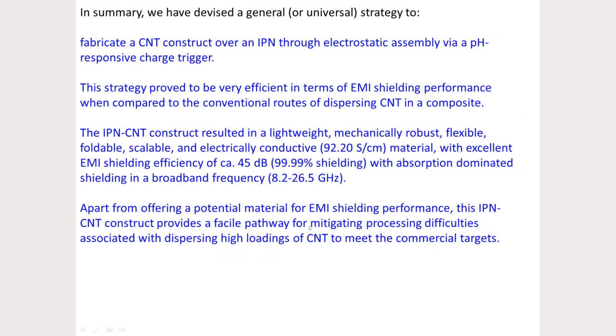So in summary, we have designed a general, universal strategy to fabricate a CNT construct over an IPN through electrostatic assembly. This strategy proved to be very efficient in terms of shielding performance. The construct is quite lightweight, as I showed you, and mechanically robust, because we have subjected these membranes to different bending cycles, and it could withstand 10,000 bending cycles. It shows a very high conductivity and a very high shielding effectiveness of about 45 dB in a wide frequency range. Apart from this, it offers a potential material for EMI shielding performance. So IPN CNT constructs could be a universal approach to design materials that can effectively shield electromagnetic radiation.